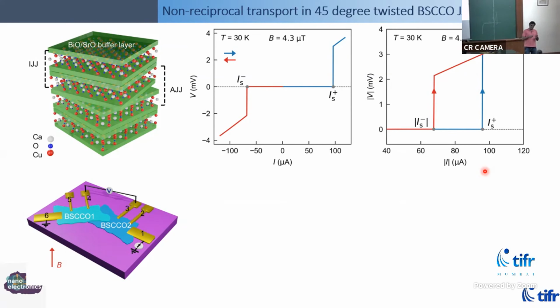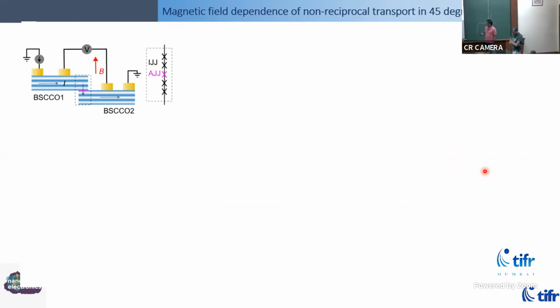Lateral, okay, good question. Lateral displacement doesn't matter as long as there's translational symmetry of the lattice, which to zeroth order is there. Rotation is sort of the key thing. Lateral translation will happen. When you rotate by angles like 45 degrees or some strange angles, they're anyway not going to be a stable crystal structure. Here it's slightly better than graphene, where actually the layers will relax to minimize the energy. Here, because there are thicker layers, they are not. So I hope I answered the question.